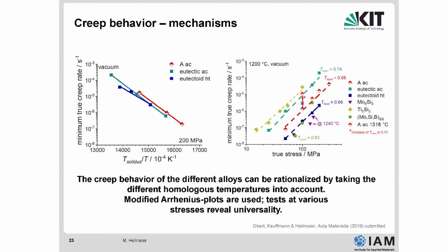So this alloy, for example, the red alloy with this temperature has a homologous temperature of 68% of the melting point. Now, the green alloy, the eutectic one, has a homologous temperature of 74% of the melting point. We made a simple test. We increased the temperature for this alloy to the same homologous temperature as the eutectic alloy, and this is shown here. This was then the creep response.